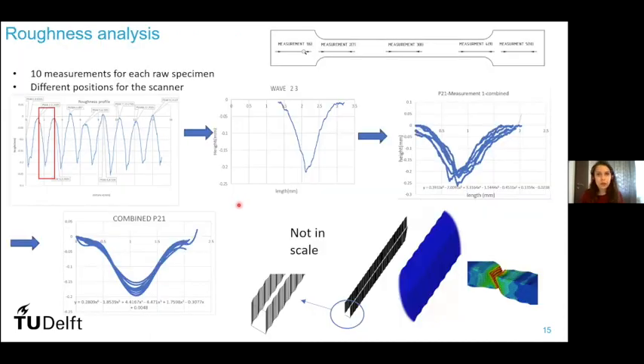Also, for these types of specimens, the roughness is really important. Even though in the beginning we measured all the specimens with a caliper, my professor scanned all the raw specimens with a 3D scanner. He made 10 measurements for all the raw specimens with different positions for the scanner, like in the picture above. 5 of the measurements were made on one side of the specimen and 5 on the other side. And then I analyzed all the data that he gathered.